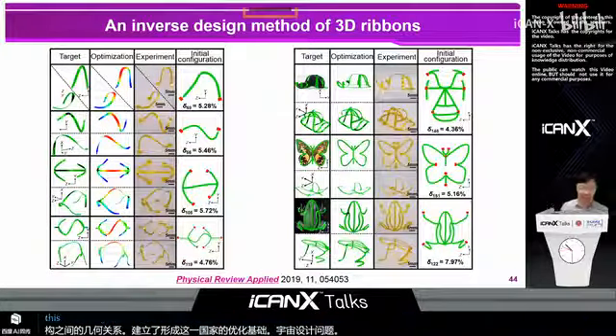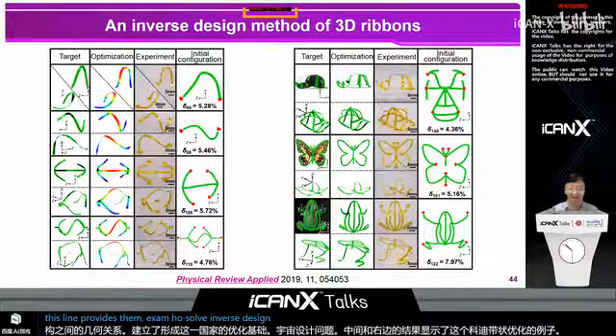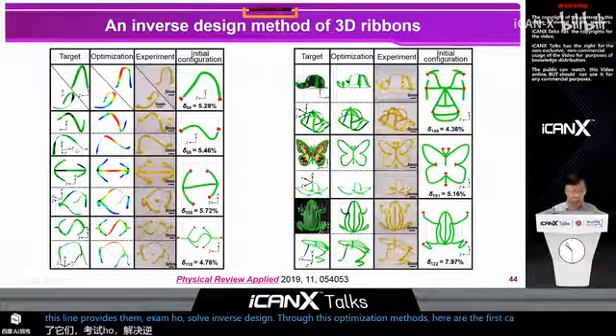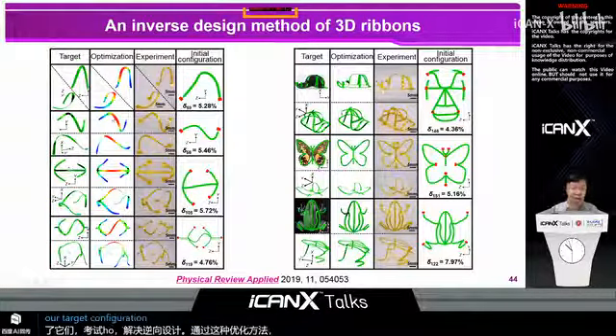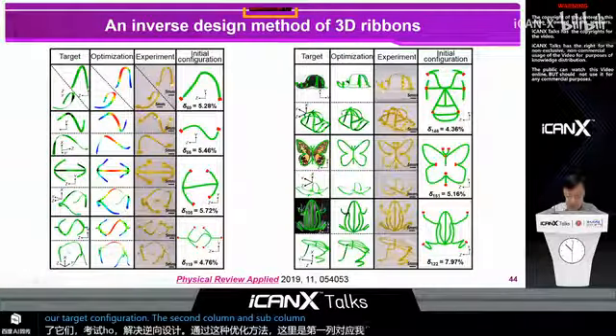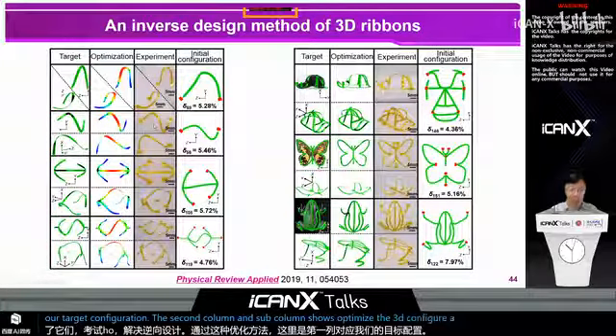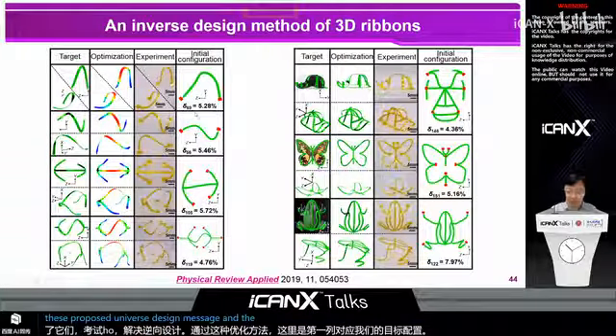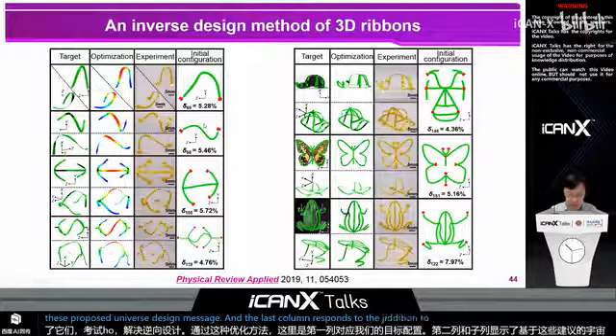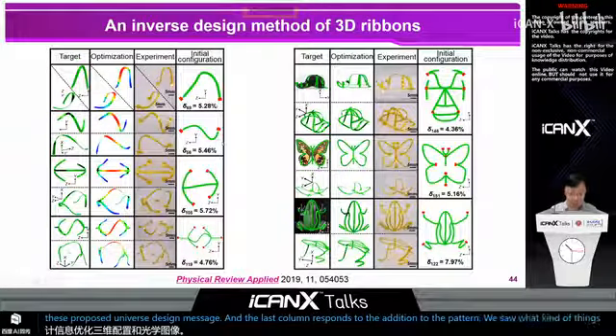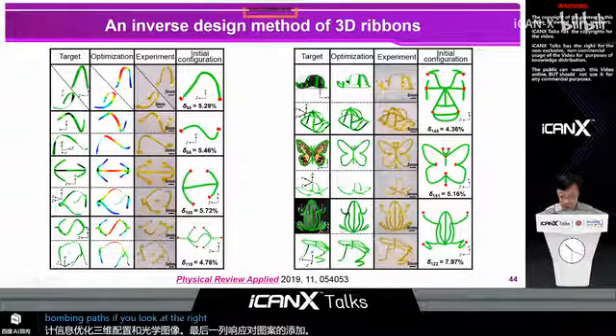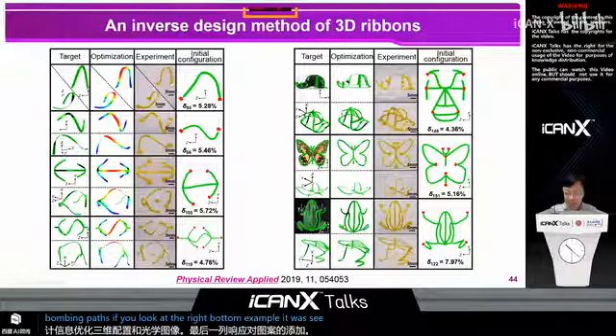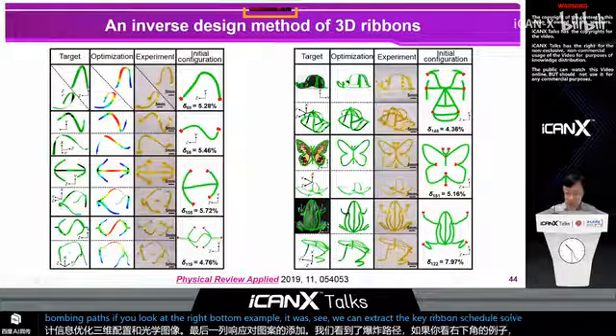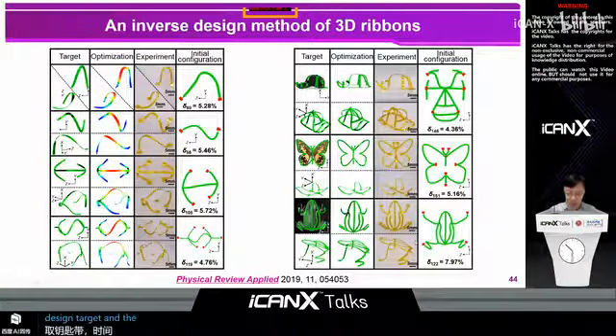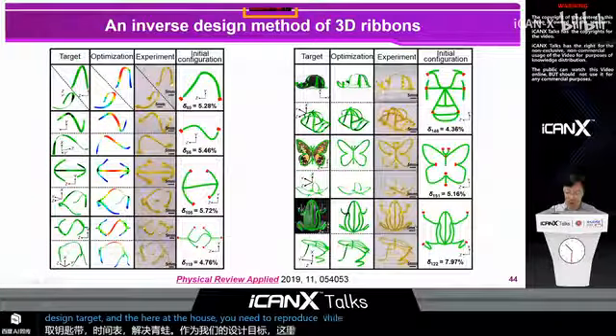And this slide provides some examples of inverse design through this optimization method. Here, the first column corresponds to our target configuration. The second column and third column show optimized 3D configurations and optical images based on this proposed inverse design method. And the last column corresponds to the initial 2D pattern with the red color denoting the bonding paths. If you look at the right bottom example, you will see we can extract the key ribbon sketches of a frog as our design target. And here the experimental results indeed reproduce well this desired 3D configuration.